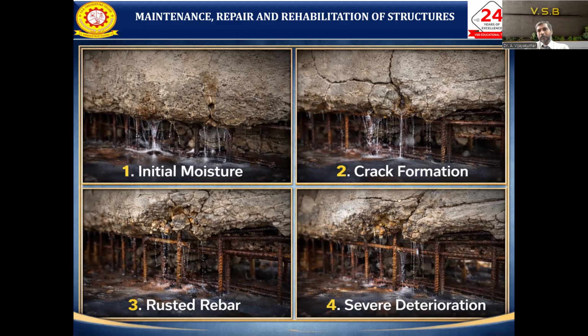So after some time, the reinforcement below, in the beam also, everything starts to rust. Okay, over a period of time, severe deterioration happens to the entire concrete surface. In severe deterioration, it is very difficult to repair. So our ultimate aim, when you see permeability, is that we need to arrest it immediately. So this is very important for our concrete structures.